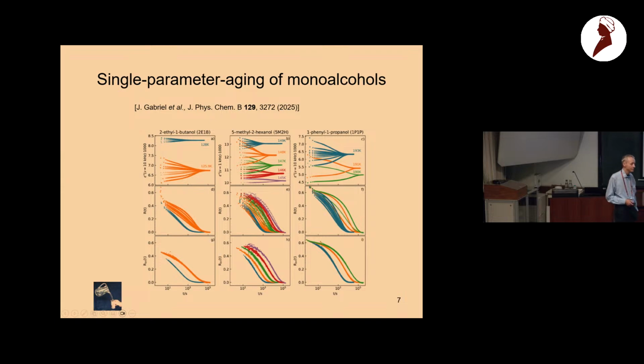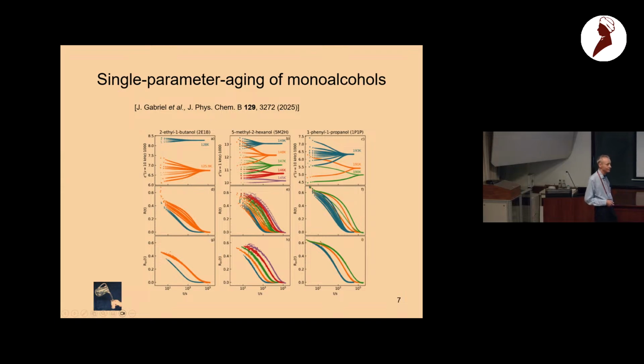But it doesn't change the fact that you have many slow processes, and it doesn't change the fact that you have a single parameter. It's a good question. You mean you're thinking about the Debye process? It has a very weak thermal signal in many respects, so that's not a problem. Here we measure, actually he ended up taking the imaginary part, but usually we take the real part, and it's basically a measure of the density in the capacitor. So the Debye process plays no role. But we were not sure it was going to work. That's why we did this.